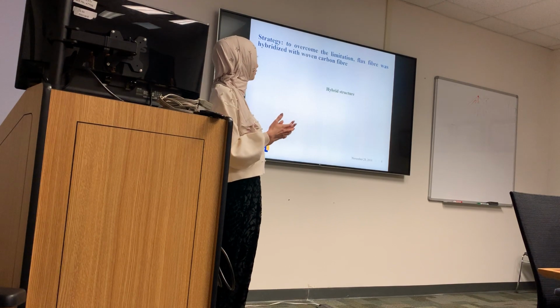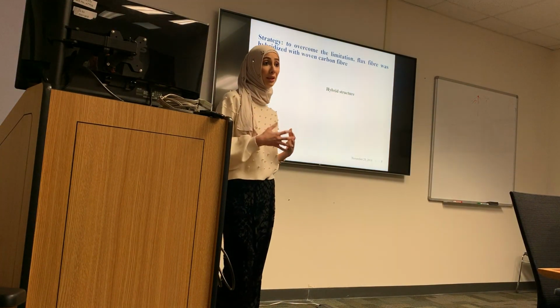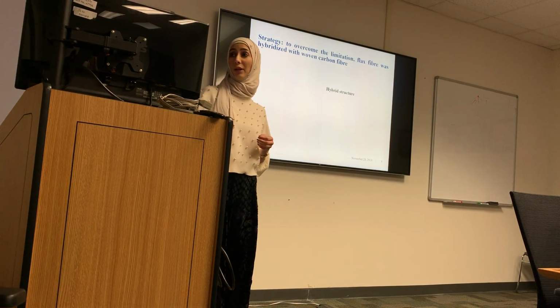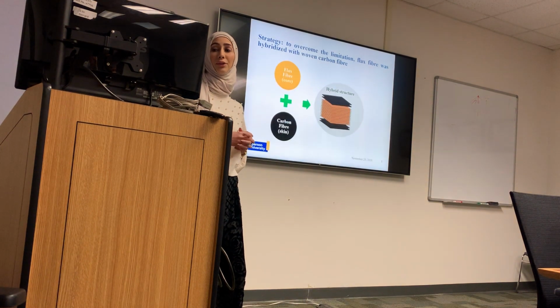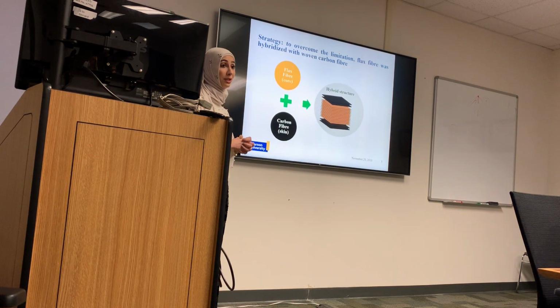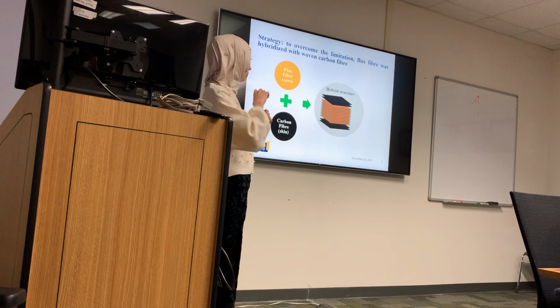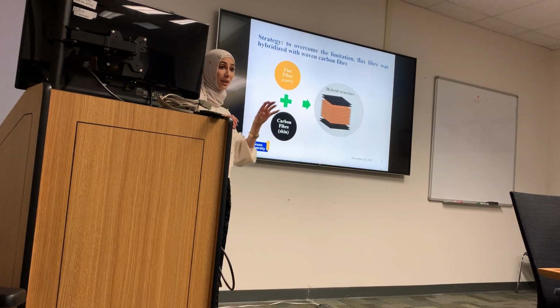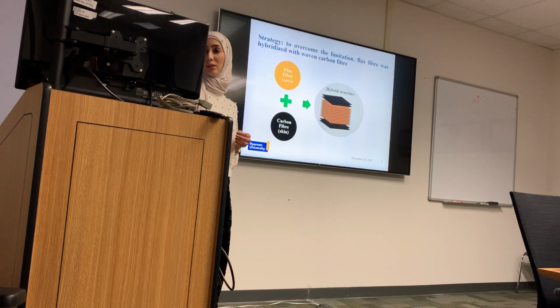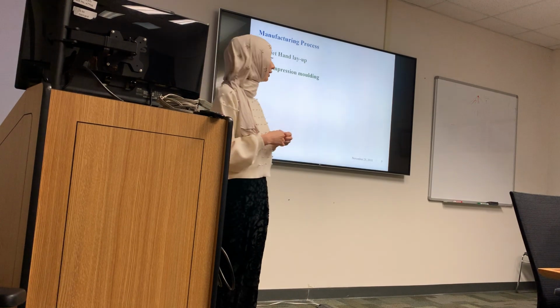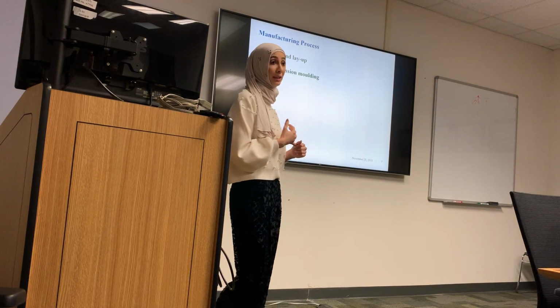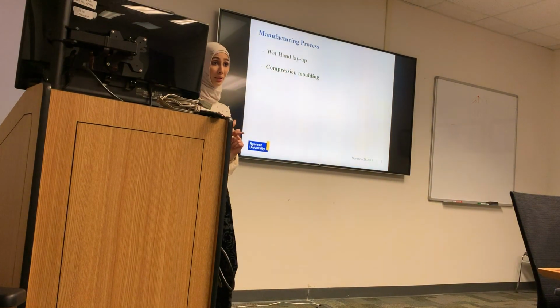As a method to overcome the limitations of flax fiber, I hybridized the flax fiber with a low content of carbon fiber. As you see, there are 2 layers at each side, a hybrid sandwich around 12 layers of flax laminate. I manufactured the composite using a wet hand layup technique followed by compression molding.